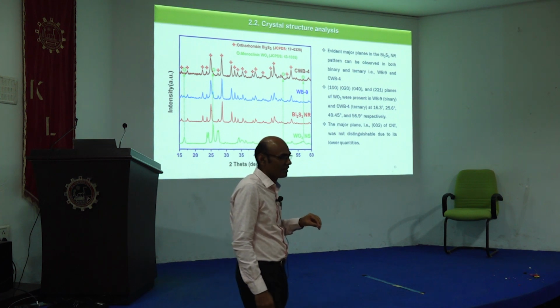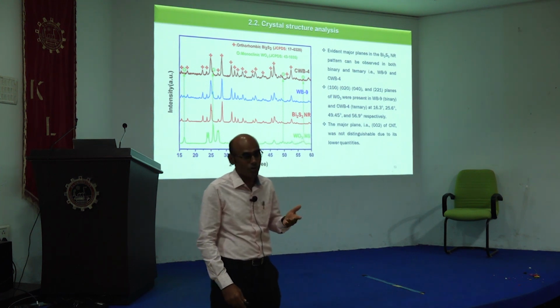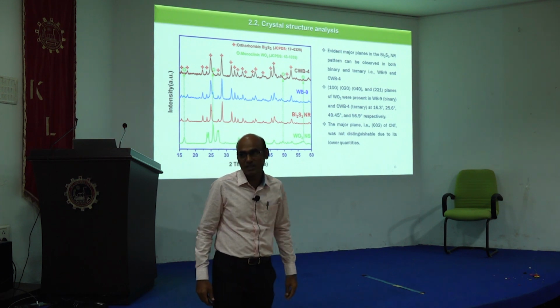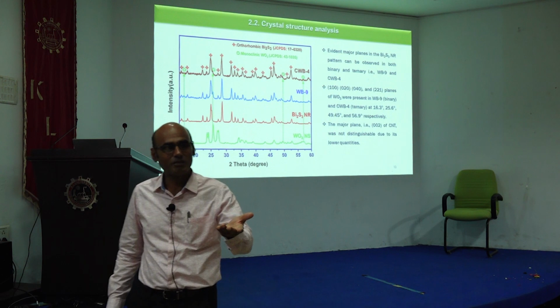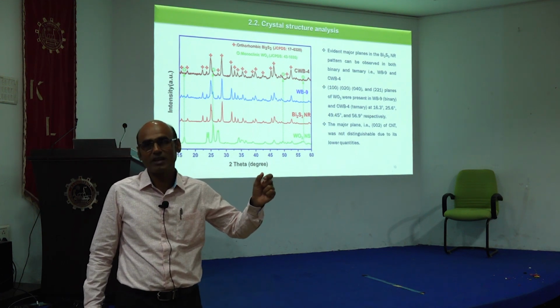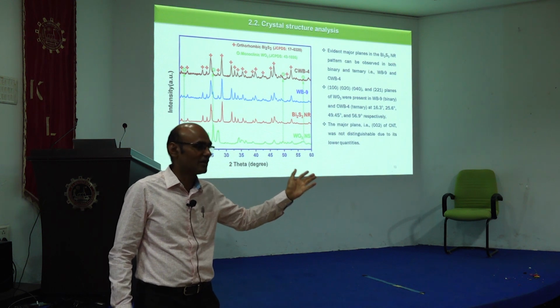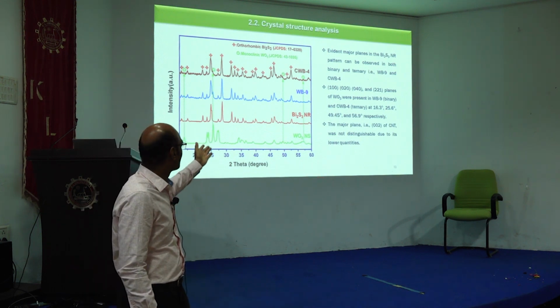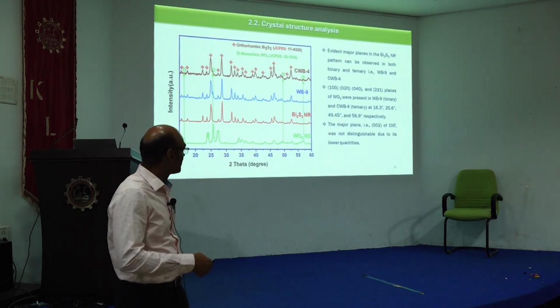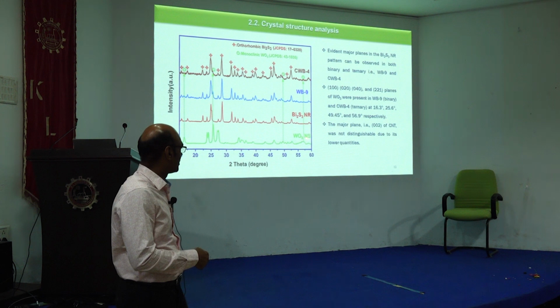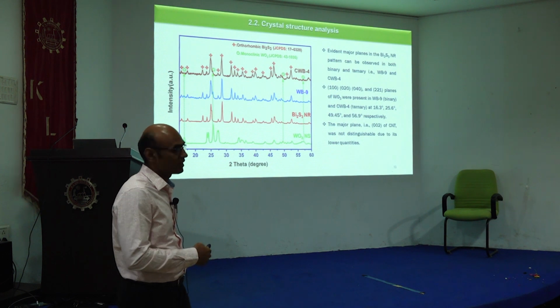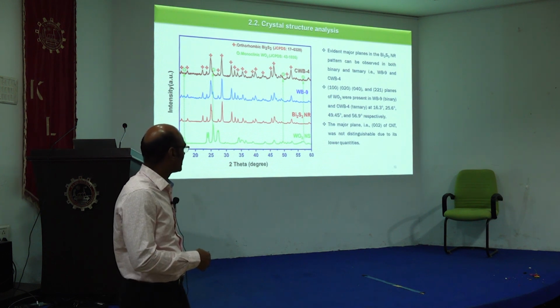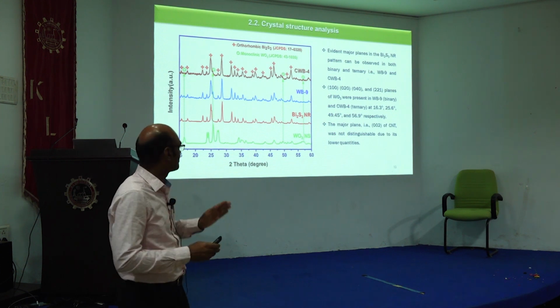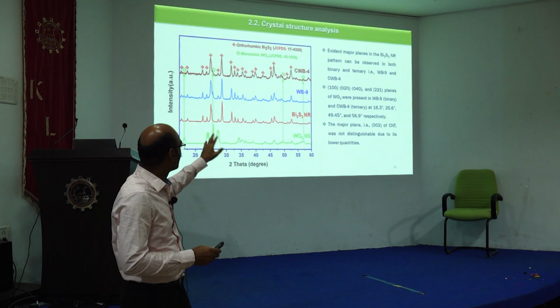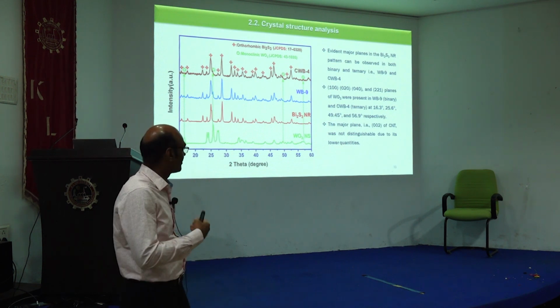So we have prepared the material, and in many materials publications you will get bored seeing many such figures, the X-ray diffraction pattern. Once I or you prepare the material, for any inorganic material you first go for XRD, the X-ray diffraction pattern. We compare with ICSD data and confirm whether we have got the material or not. Similarly we checked the pristine nano tungsten trioxide and the pristine bismuth sulfide, and then the binary composite and the ternary composite also. The pristine materials show planes matching the standard diffraction pattern, the composite has a mixture of both, and the third one with carbon nanotube has all three.